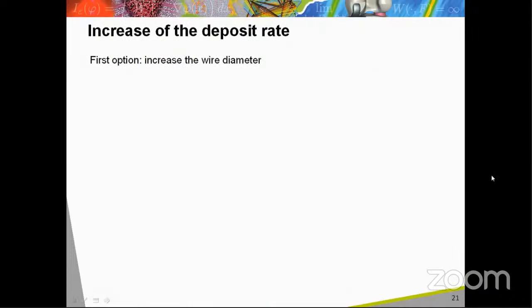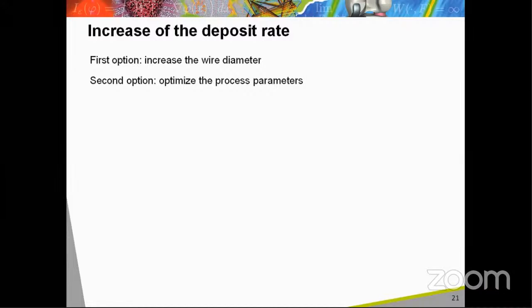The first example of process parameters optimization that I will present concerns a study focused on the increase of the deposit rate. The first option to increase the deposit rate consists in increasing the wire diameter. For some current materials, the welding devices allow using wire up to 1.6 mm in diameter. However, these wire sizes are not available for all the materials, the standard diameter of the wire being 1 or 1.2 mm. The second option consists, of course, in optimizing the process parameters.